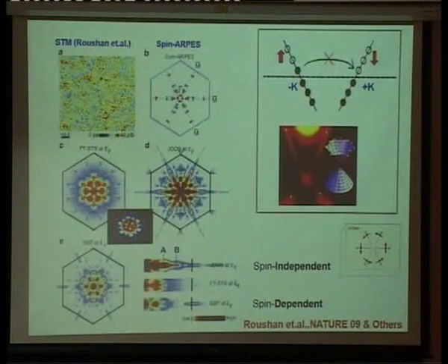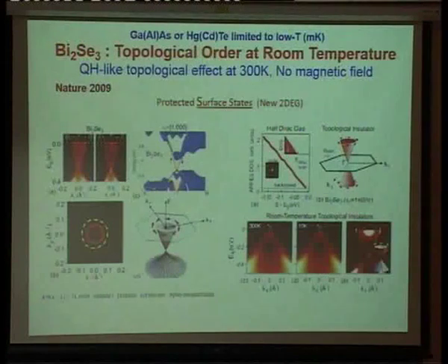But in this case, we are just using a material that has more surface states to prove it on a more general ground, so that when you consider the Fourier transform of the STM signal, you can see that there are missing peaks. So in other words, the interference has spin dependence to it, and the only way to connect ARPES and STM consistently is to suppress backscattering.